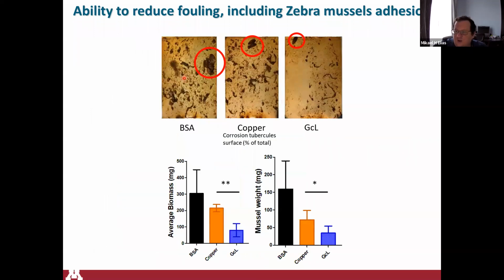If you have a closer look, you can actually see in more detail that here you have a clump of mussels, you have a small clump, and then you just have one here. And so obviously, mussel adhesion has some stochastic effect. Sometimes you can have a big clump attaching to a surface, and sometimes you may have nothing. So what you need to do really is a lot of replication to try to avoid falling into this trap of looking at some stochastic effect. And we're working on multiple replication.